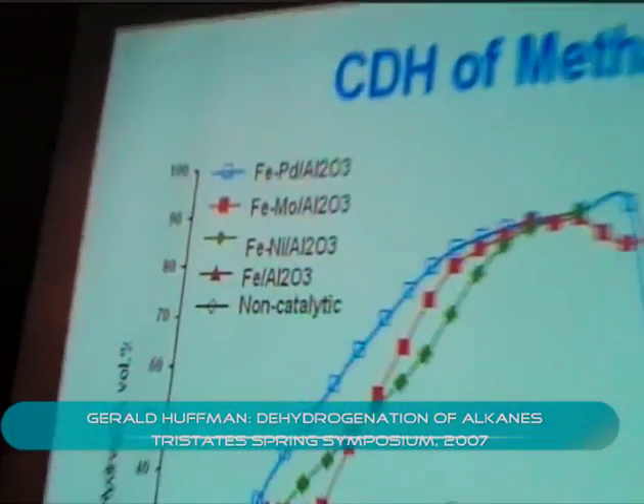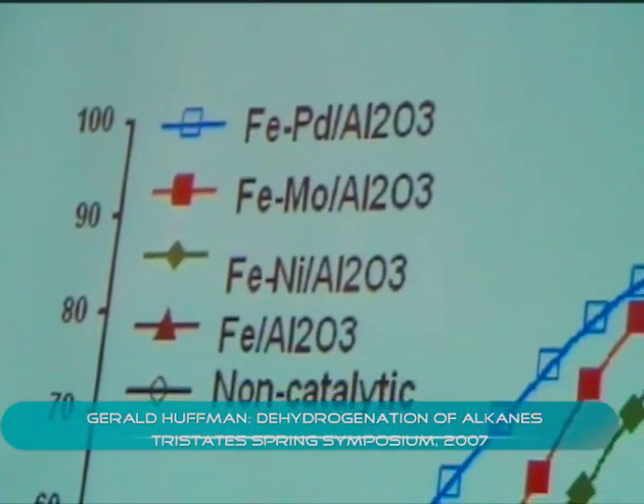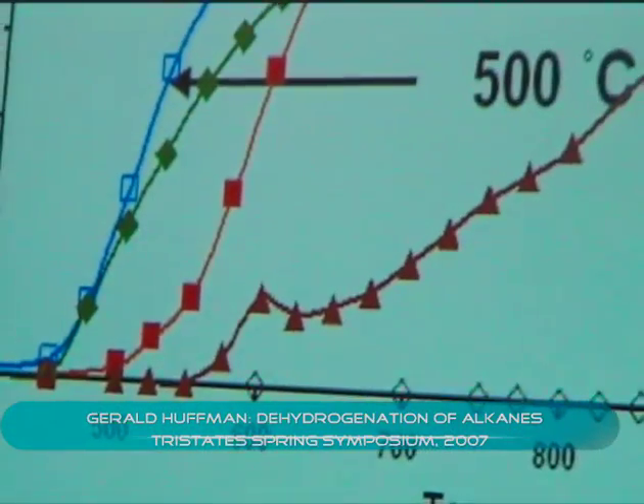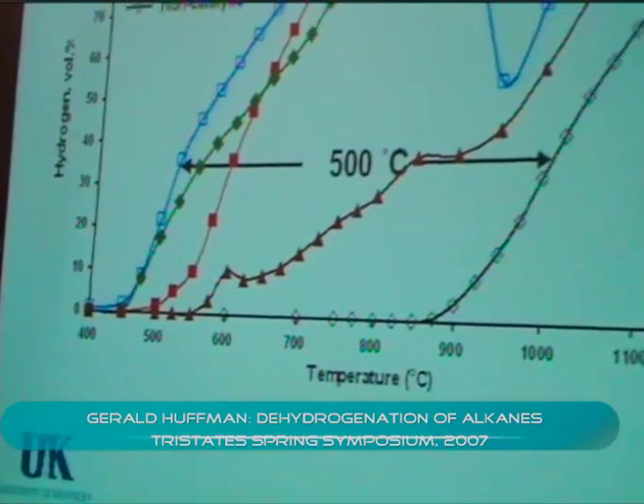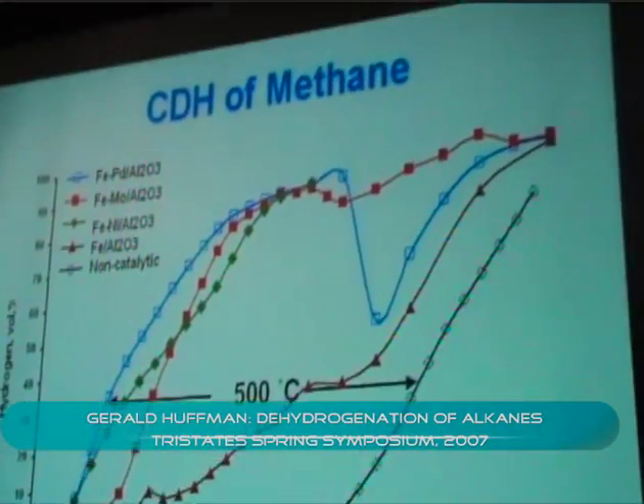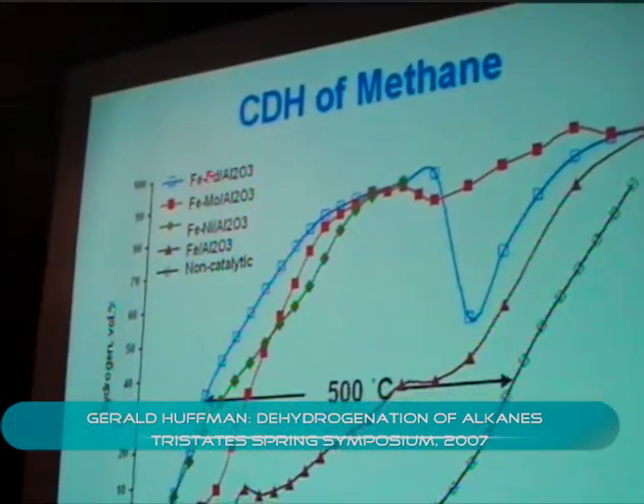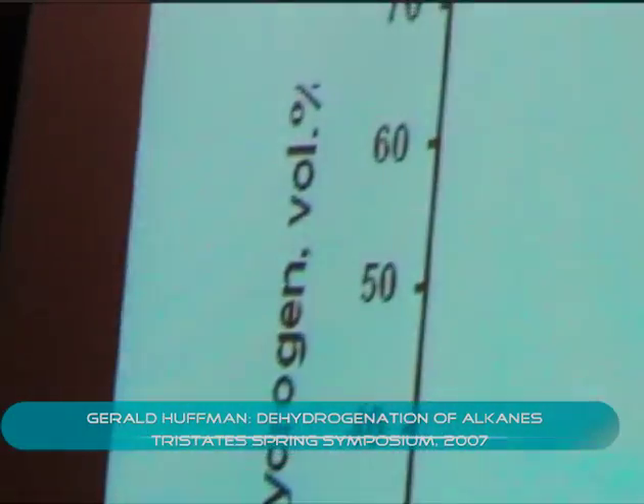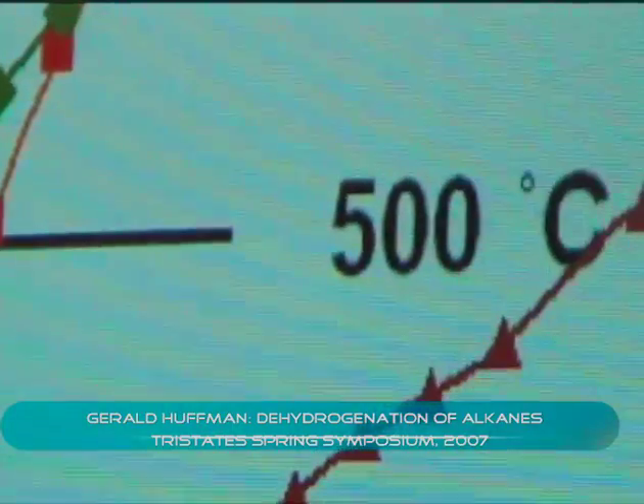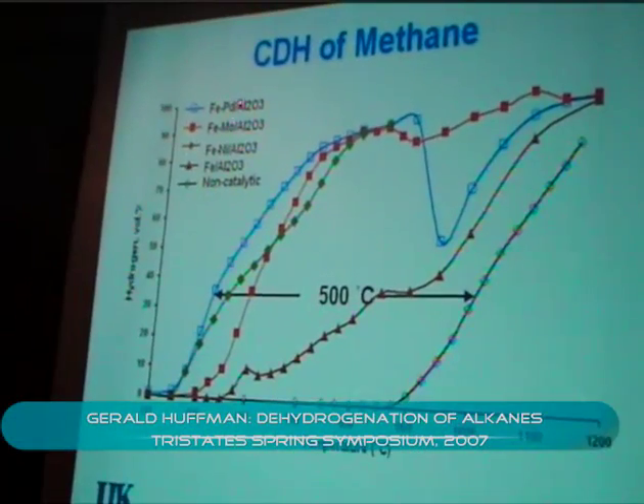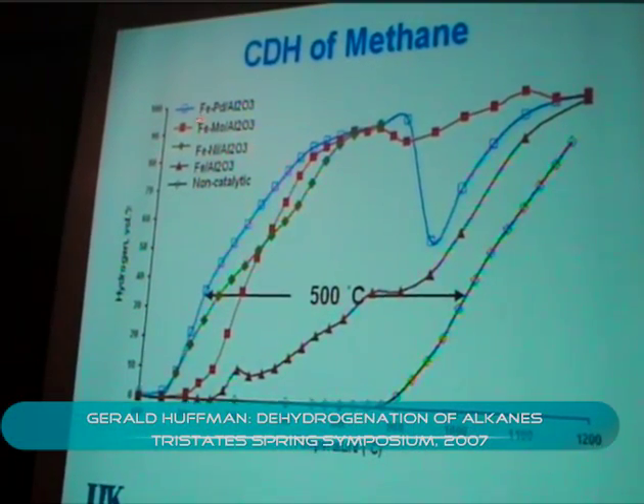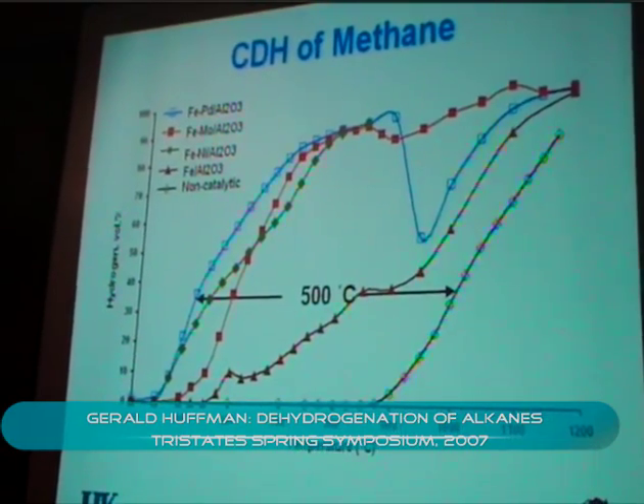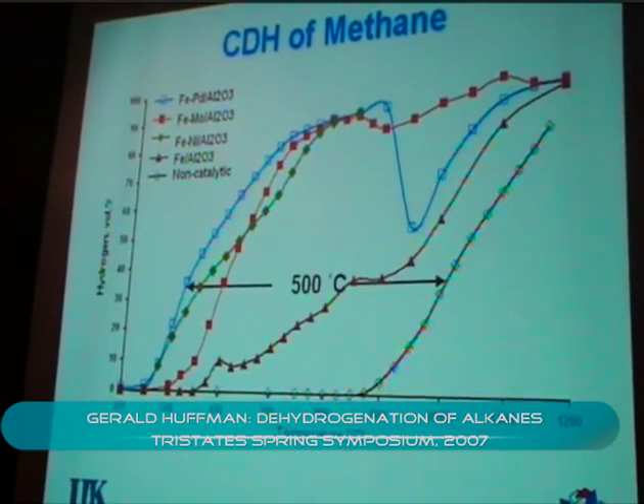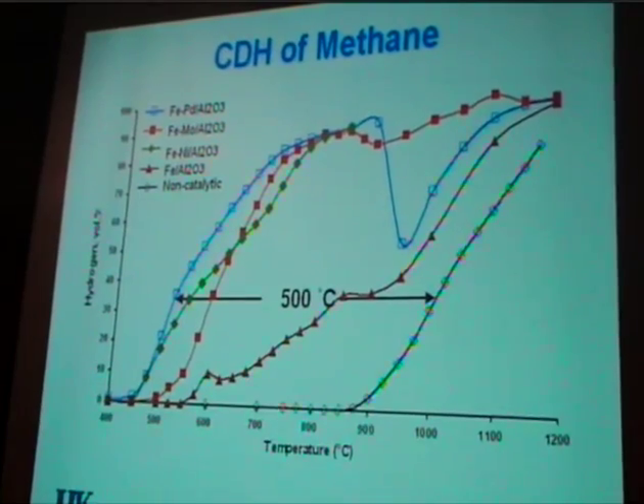nanotubes. This shows the hydrogen production from catalytic dehydrogenation of methane. The balance of the gas is methane. That's all that's produced, hydrogen and methane. And we're looking at it for 3 different catalysts: iron palladium, iron moly, and iron nickel. Catalyst loading is about 5%, and the iron to secondary element is about 70 to 30.